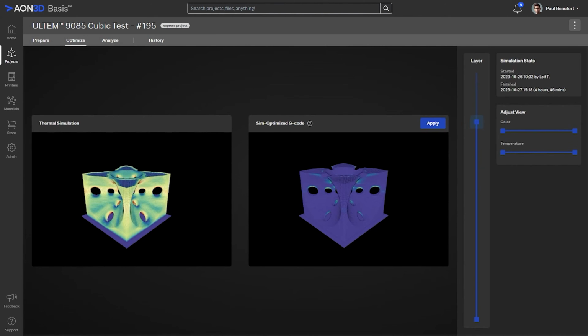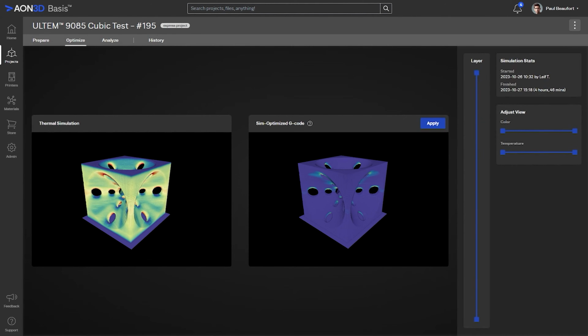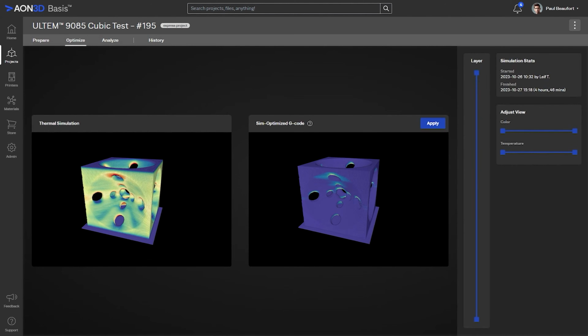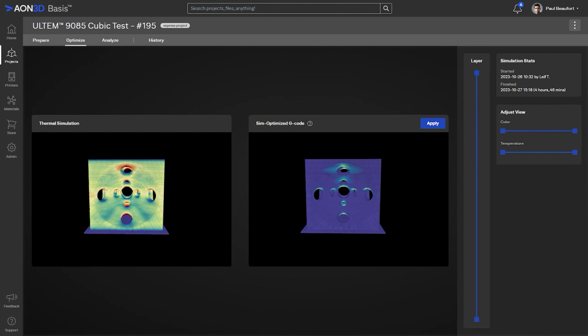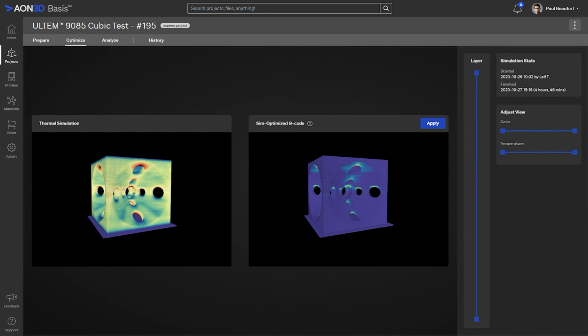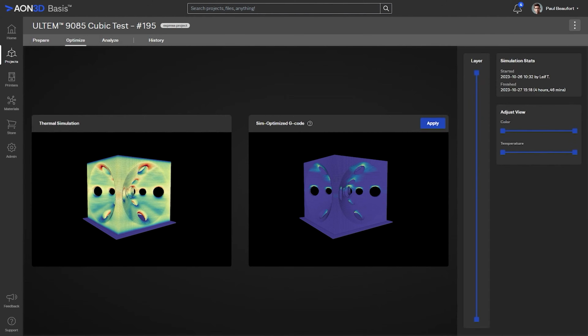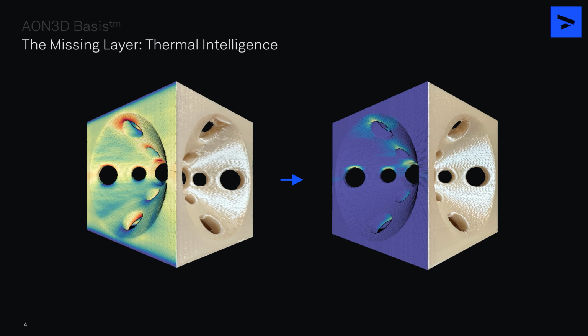This is not a temperature plot, but rather it's showing areas it's identified as being likely to overheat and create visual defects or compromise mechanical performance. So how does that pre versus post optimized artifact look in practice? Here on the left, we see that the areas that were identified as overheating did indeed overheat, right?